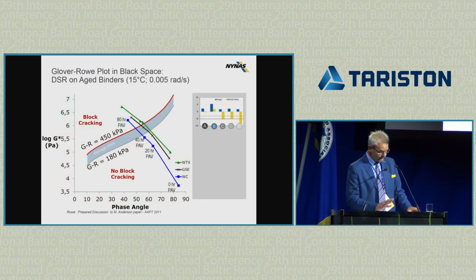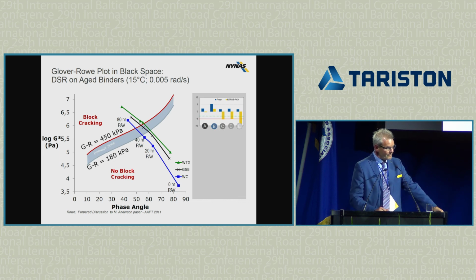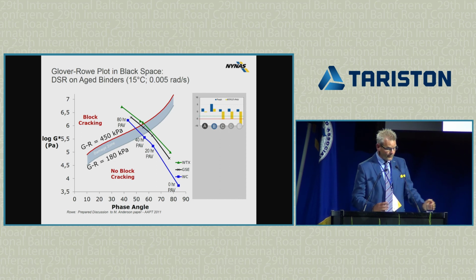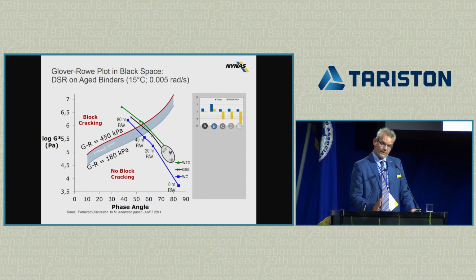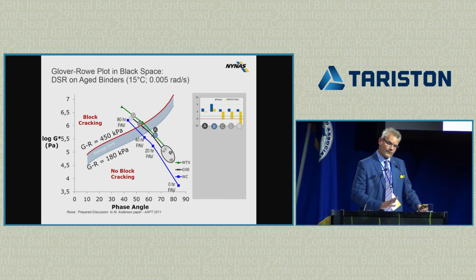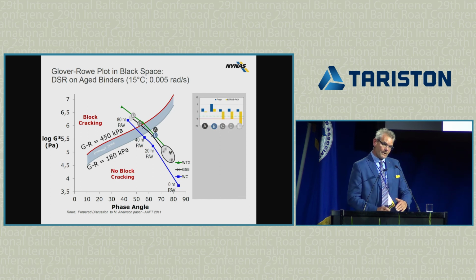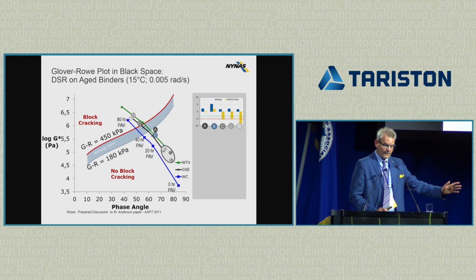When we talked about delta TC, we've also looked at these materials in Glover-Rowe, and Professor Pellinen has already shown this picture. And we can plot those 5 binders that we tested in the laboratory as well. They look very much the same. They start at the bottom right-hand corner when they're fresh, not aged. But when you start to age these materials, you will see they go up, move into the cracking area. Here you can see that the bitumens A and B that perform the best in delta TC, they remain in the area where there's no block cracking, while the bitumens that show a high negative value of delta TC, they are in the blocking area.